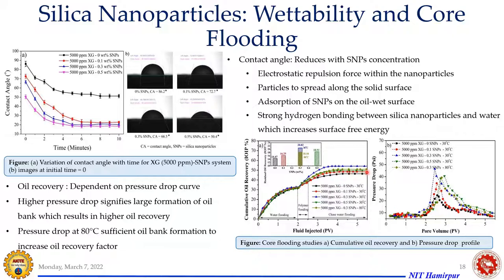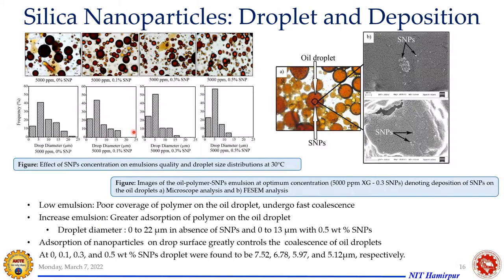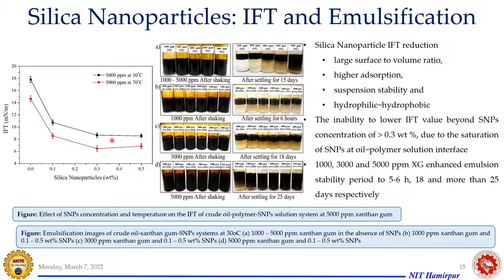And as we keep on increasing the nanoparticle concentration, you can see at 0.1 we got around 16.3%, at 0.3 we got around 20.8%, and at 0.5 we got around 18.5%. So you can see here that at 0.3 we get the highest recovery, and at 0.5 we get lower recovery. And why is it so? As I've told you, the nanoparticles are reaching the saturation point, and that's why the recovery is decreasing.